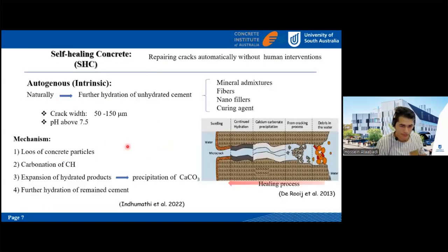As you know, self-healing concrete refers to material that can heal itself without any intervention. Concrete has a very intrinsic healing performance, which we usually call autogenesis. That happens because of further hydration of unhydrated cement inside the matrix, and it can be improved by addition of some mineral admixtures, fibers, nanofillers, or even curing agents. This autogenous process mostly happens in pHs above 7.5, so we need an alkaline environment for this healing to happen.